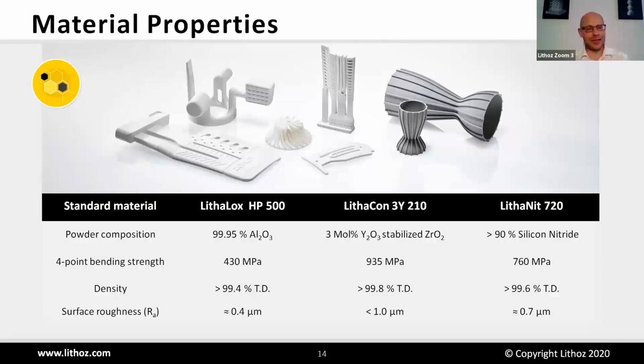So we are having densities well above 99%. We have the four-point bending strength. These are the two most important issues, density and strength, and they are the same as in conventional forming technology. And something which we are very proud of as well is that just by using the printing itself, we can reach very good surface roughnesses. We are well below 1 micron Ra value. You can check them out on our website.